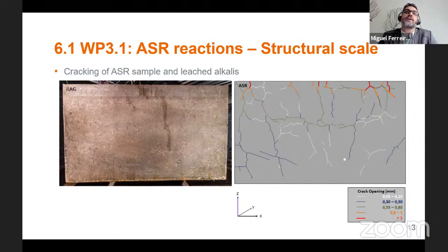So here you have a visual aspect of the ASR block. I hope you can see that clearly. The cracking is maybe not so visible in the block. So these deformations and the crackings were tracked in the block for more than 3 years. And obviously the cracking is not uniform. The cracks filled with white precipitation, which we measured to be calcite.